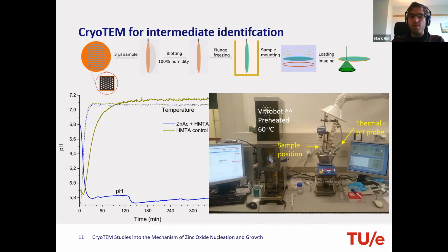And then we also found some additional complications. When you perform this reaction in a fume hood, you can set your watch to it, and it always takes 2 hours plus or minus 5 minutes before you get the second transition. However, the moment you start sampling from some point in the reaction, this shifts to earlier time phases.